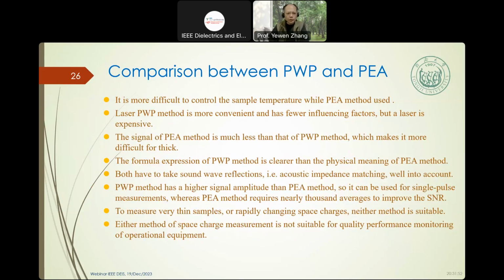But we'll continue the comparison. It is more difficult to control the sample temperature in the PEA method, because we are measuring the acoustic signal using the PVDF sensor, which also needs temperature change. The laser PWP is very easy and convenient, with few influencing factors, but the laser is expensive. But the signal of PEA is much less than the PWP method, so it makes it more difficult for thick samples.